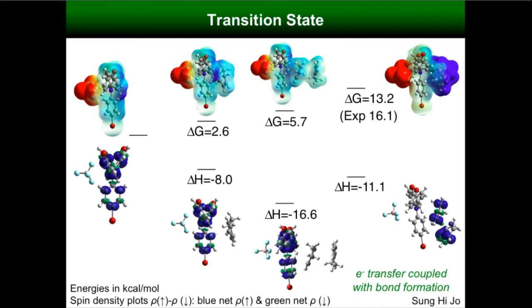Looking at this reaction computationally, what you find is that this first initiation step that's uphill, the electron transfer event, and so the bottom blue pictures are showing the path of the electron. What happens to the electron, the unpaired electron, as a function of reaction. The reaction enthalpy is going downhill. You're binding the cyclohexadiene. This is going downhill, but the top is showing red is negative charge, blue is positive charge. Before the transition state, the electron transfer event hasn't occurred, but at the transition state, the electron transfer event is occurring. And so it isn't, if you will, a classical outer sphere reaction. It's more of an inner sphere coupled electron bond forming process.